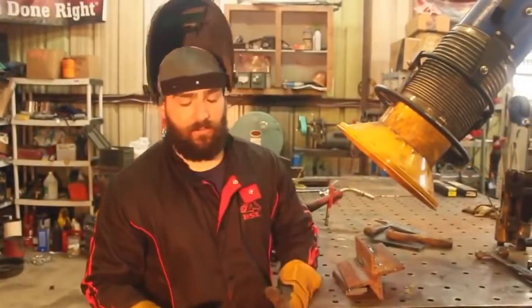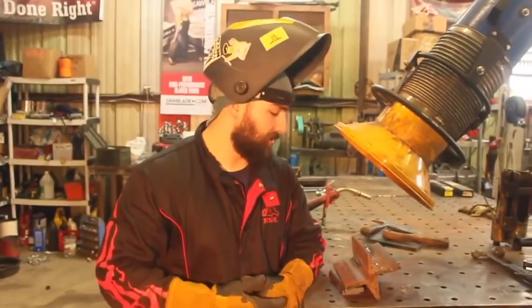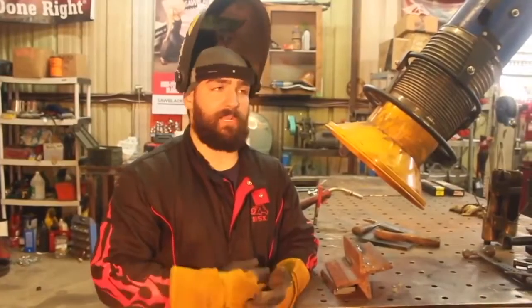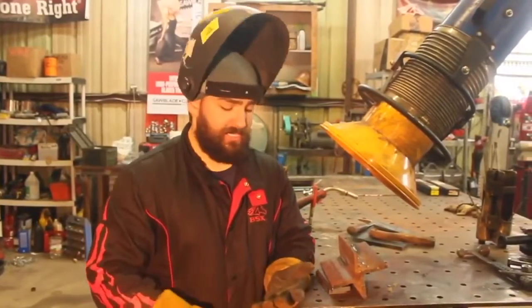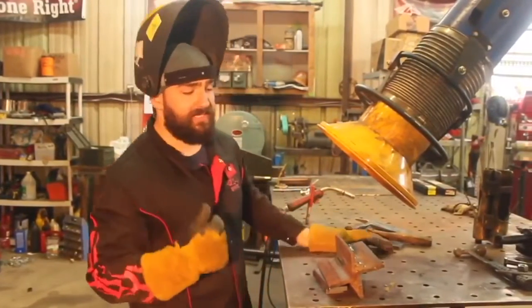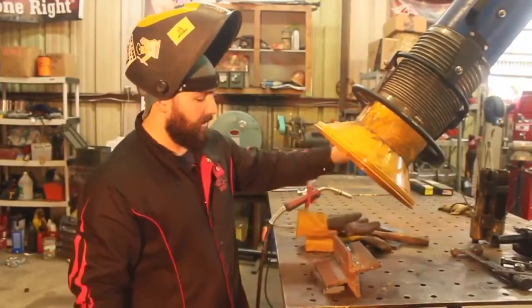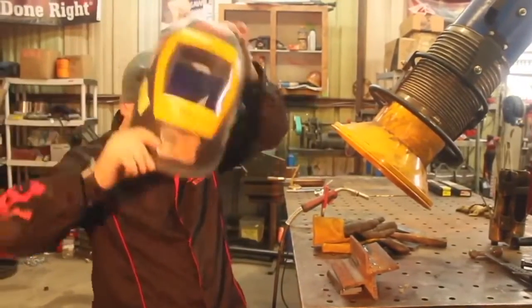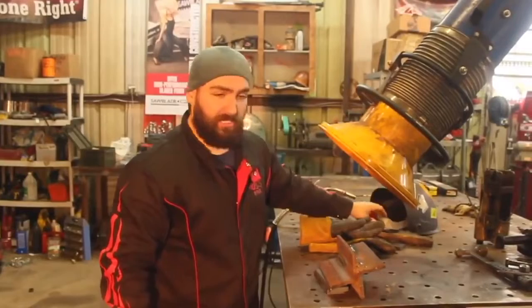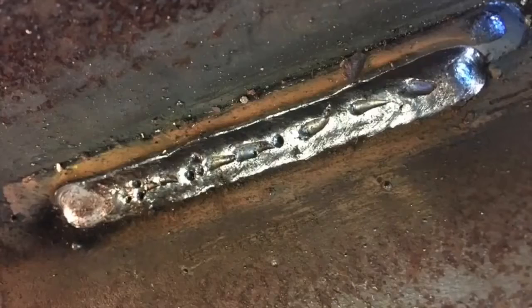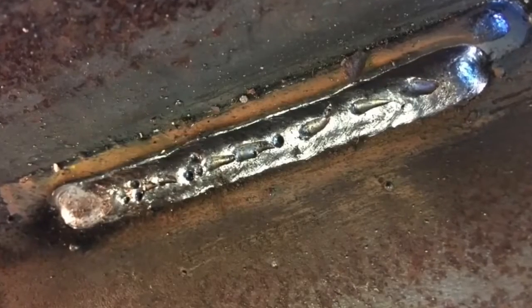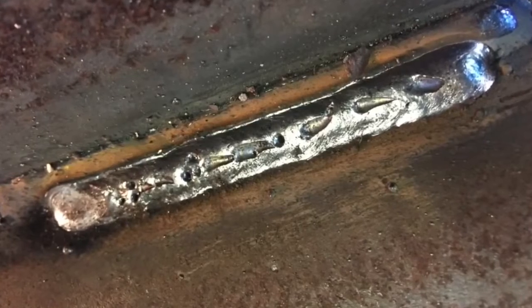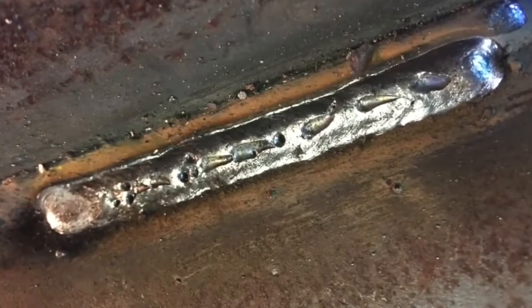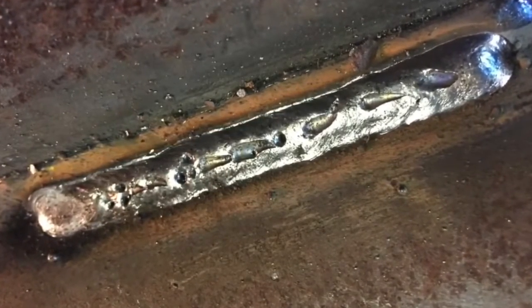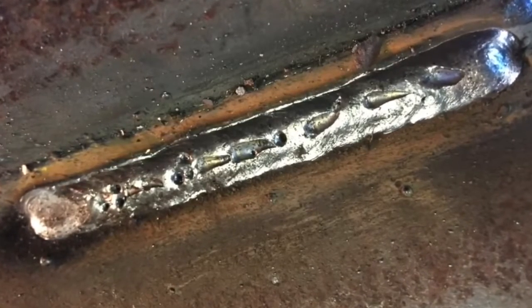You have two different types of porosity. You have actual porosity in the weld, which is caused by a number of different things: dirty material, your flow rate not set correctly on your flow meter, incorrect shielding gas, and things of that nature. Then you have what's called surface porosity, which a lot of times can happen from your diffuser, the frit, your gun angle, or your flow rate being too high. So there's two sides of the spectrum as far as porosity is concerned.